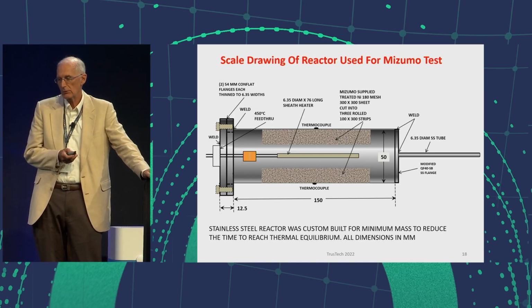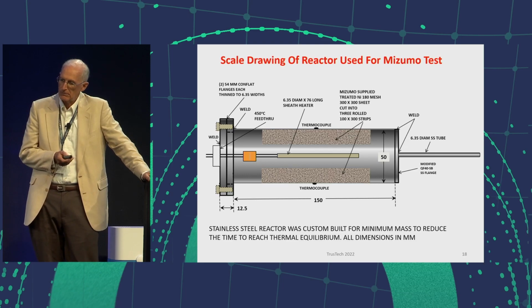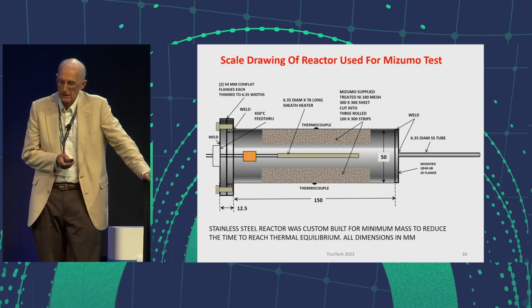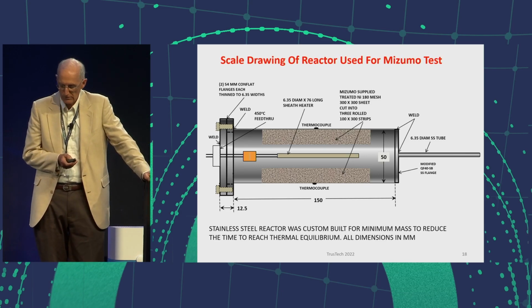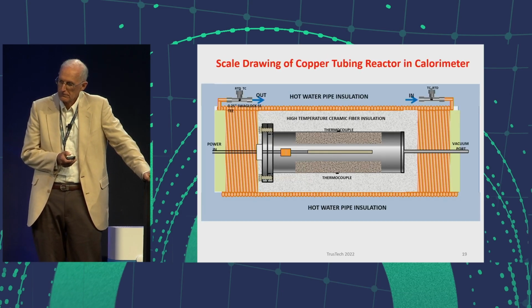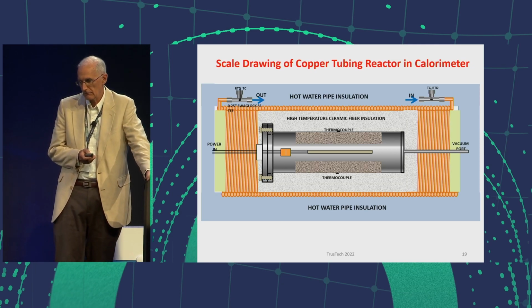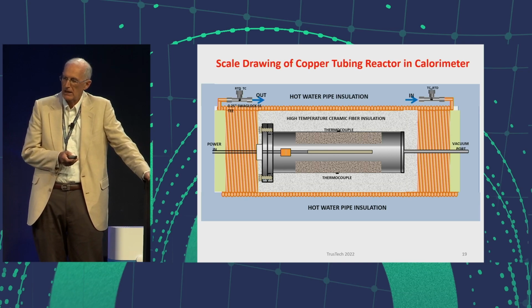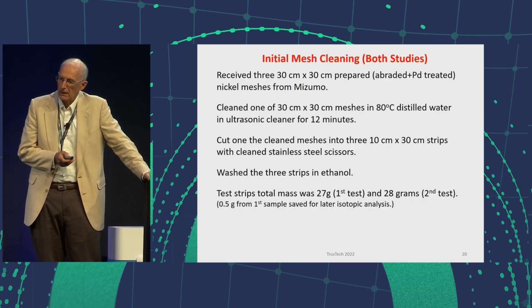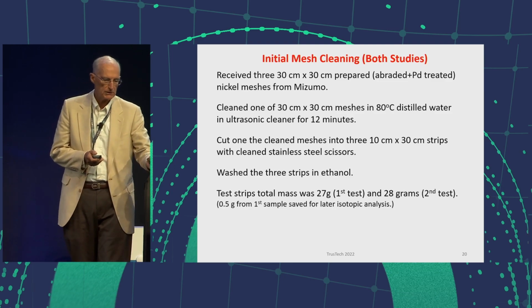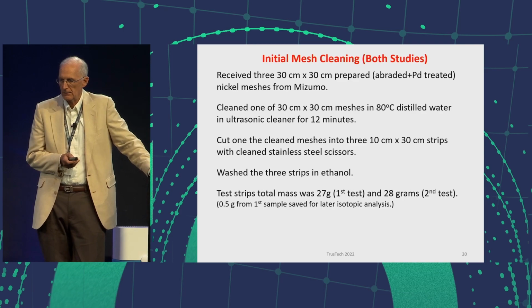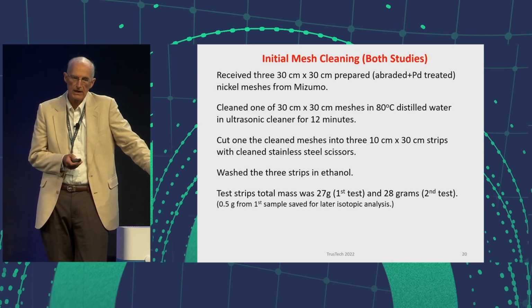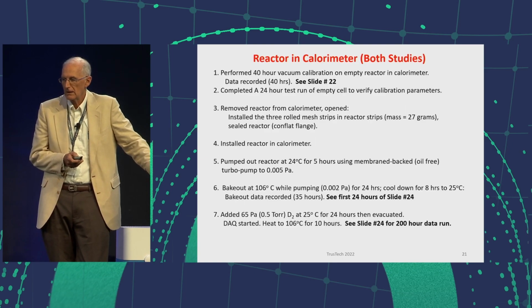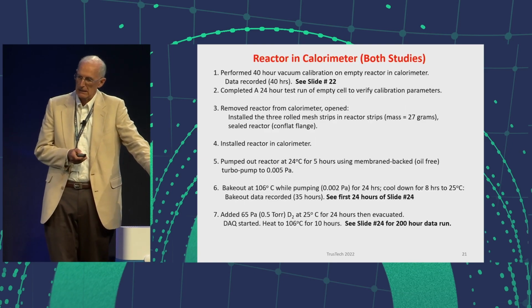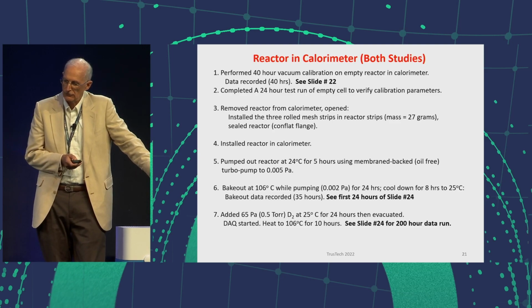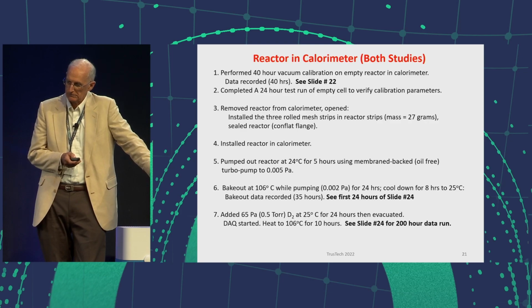So around the outside are the 3 levels of the nickel mesh, and in the middle goes the cartridge heater, and it allowed me to measure the pressure during the experiments. This is a scale diagram of the cell inside the calorimeter. This system, there was a cleaning procedure that Mizuno did before the mesh was put in there, and this is the procedure that I followed for both samples. There was also a procedure to use inside the reactor, and so I followed his procedure also.